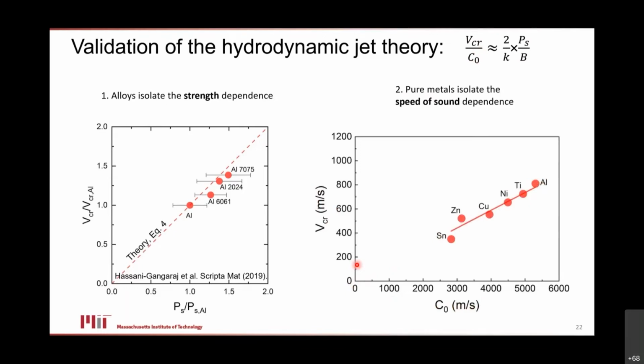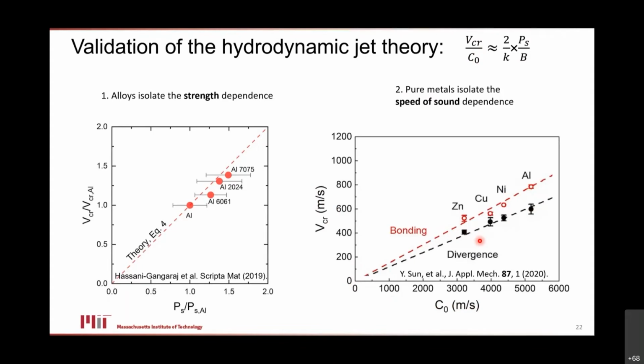And by the way, that turns out to be true not just for one critical velocity. These data are for the critical velocity to bond the particle. It's true also now for that independent measurement. This is the critical velocity to start a jet forming. So this is the divergence velocity, the velocity at which we first diverge from that power law. Those also obey the same scaling. And so to us, this is really convincing evidence that this is a hydrodynamic phenomenon. And if you look closely at these data, the speed of sound puts these metals in the right order and lines them up. But there's no other material property that would rank them in this way. So these things are not ranking with their strength. They're not ranking with their modulus or their melting point or their density or anything. It is uniquely the speed of sound that puts those guys on the curve.